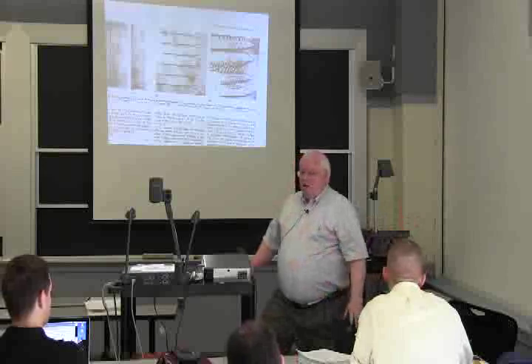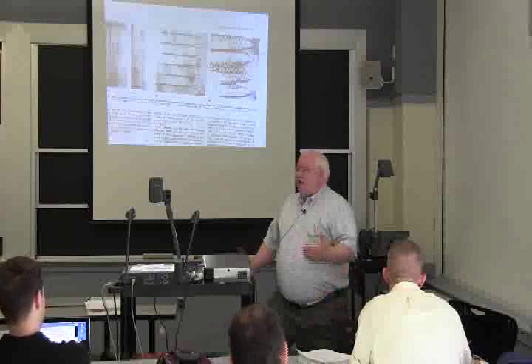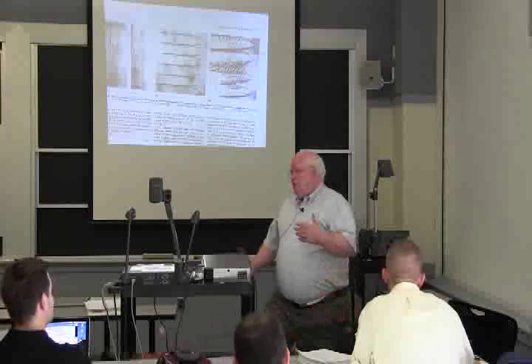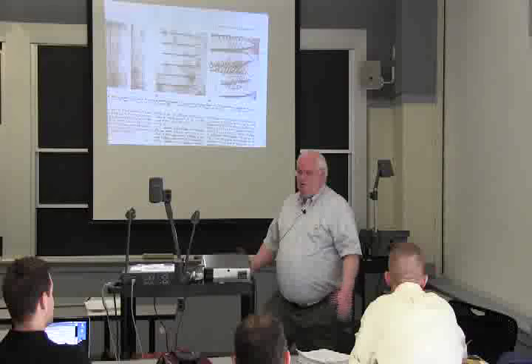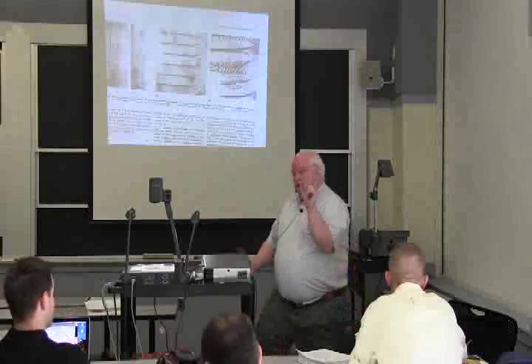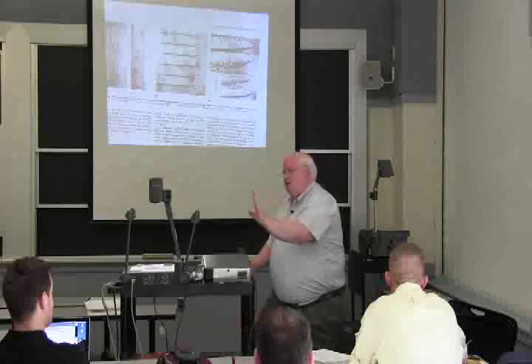The problem with the high side chemistry was it had a yield strength of about 140 KSI, not 100 KSI, because it was enriched in alloy. And if you're at 140 KSI, your sensitivity to hydrogen is much worse - you can't tolerate anywhere near as much hydrogen. It was all within the Navy spec range, but it happened to be all the way at one end, the high side chemistry.